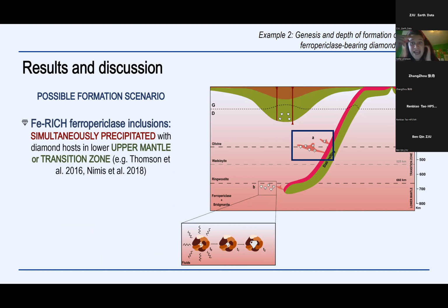The first is that the iron-rich ferropericlase inclusions within diamonds simultaneously precipitated with their diamond host at the depth of the lower part of the upper mantle or of the transition zone. This conclusion is related to the experimental results that Thomson et al. obtained in 2016, where Thomson et al. predicted that iron-rich ferropericlases with variable chemical composition precipitate simultaneously with their diamond host at depths of the lower upper mantle or of the transition zone.